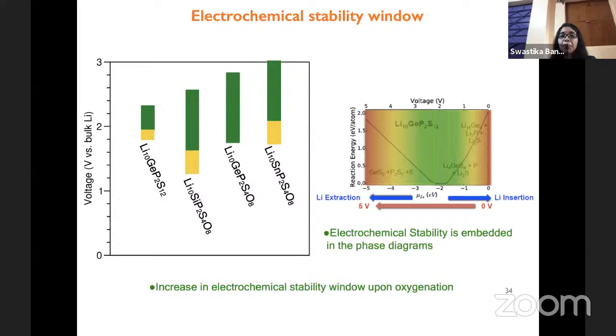So with this initial study on the stability in terms of the phase, we wanted to look for the electrochemical stability window. And we find that for LGPS, we have the stability window here in the extreme left corner. For the LGPSO or the other components, like instead of germanium, if we put the silicon or tin, we have the modulation of the electrochemical stability window. So you can clearly see the stability window is much wider in comparison with the LGPS when we have oxygen in the framework.